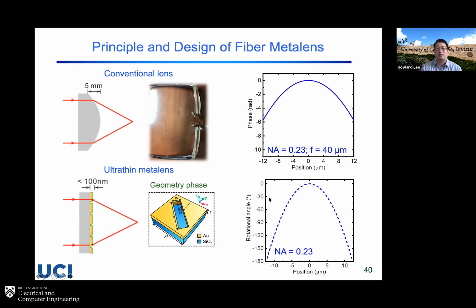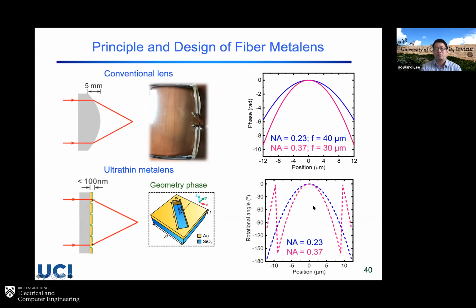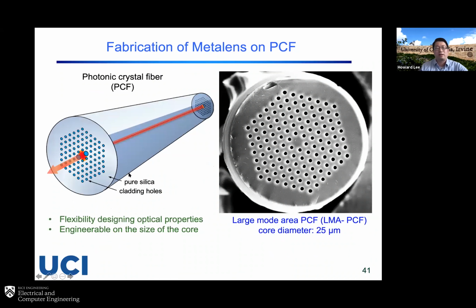So then to design the lens, this is the phase you need, and what we can do is just rotate the angle to achieve the phase profile we need to make this lens. And if you want to make different lenses, basically you have a different phase profile, then you just need a different rotational distribution to make another lens here. The fiber we have been using to make the lens is a photonic crystal fiber. I will skip some of the details here. Basically, using this kind of holey structure, you can control the light in the core. And the good thing is that you can also engineer the size of the core. So that's why we're using this as a large mode area fiber. We have a 25 micron core so that we can make more elements inside the core of the fiber here.